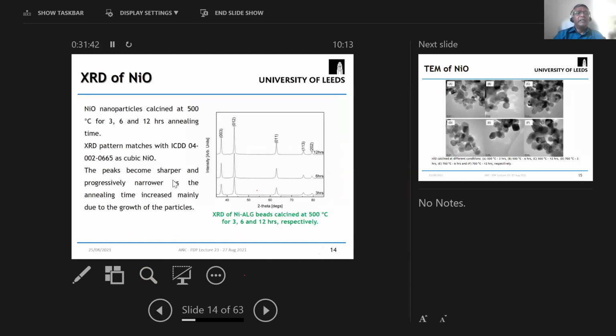So we tried to calcine the nickel alginate beads at different temperatures for different lengths of time. And you can see that this is the XRD pattern of nickel alginate beads, calcined at 500 degrees Celsius for 3 hours. And as you increase the calcination time, naturally there is a grain growth. So this is in the form of nanopowders. You can see the peaks are very broad. And it's a single phase, very, very pure nickel oxide without any traces of any impurities at all. The peaks sharpen as you increase the time at 500 degrees Celsius due to the grain growth.